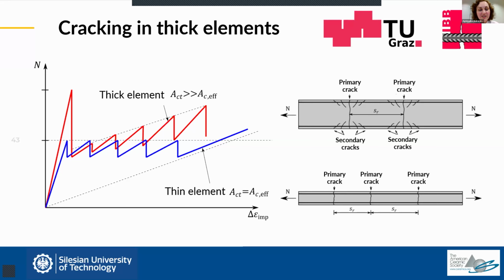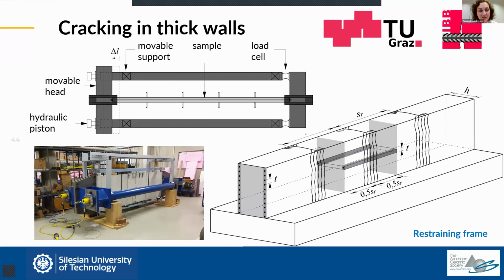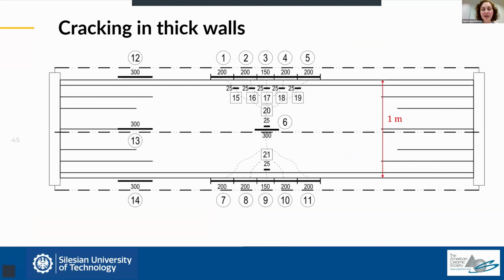We have investigated this using an original setup, which has been built by the team of Professor Schlick, called a restraining frame. In this frame, we have tested a sample which is extracted from a wall. Such a sample represents a slice of a wall at the height of one level of reinforcement, and it represents the actual thickness of the element. So the sample looks like that. Here you can see a sample which represents a slice of a 1 meter thick wall.